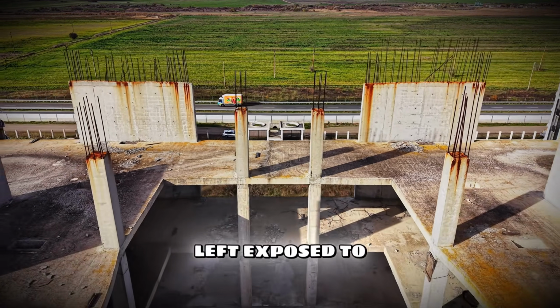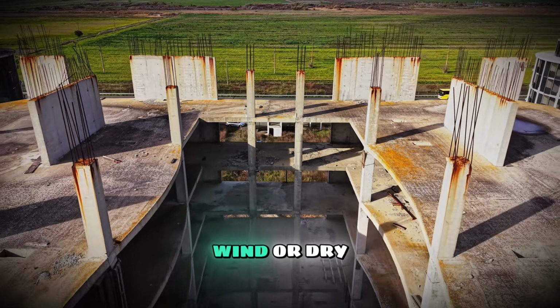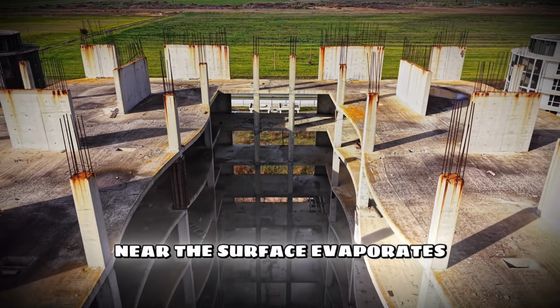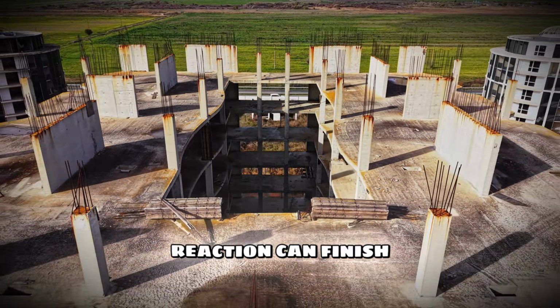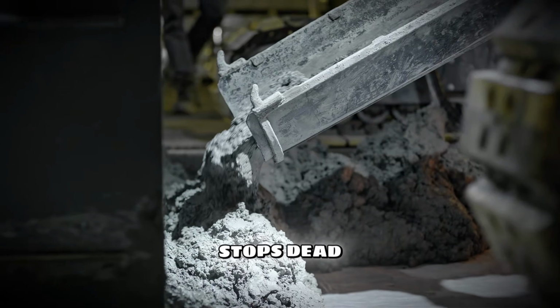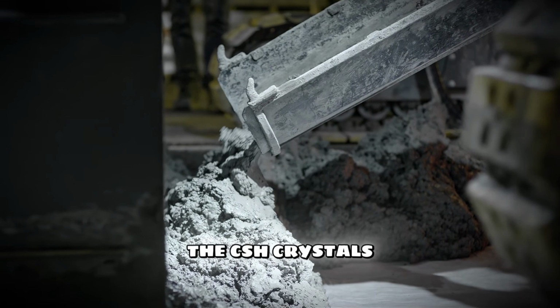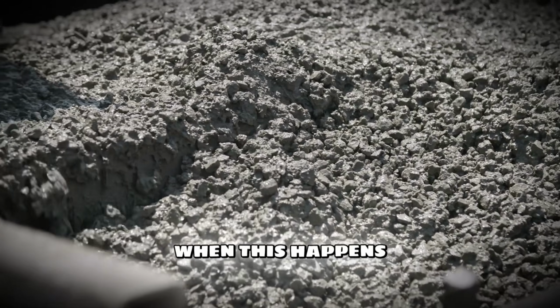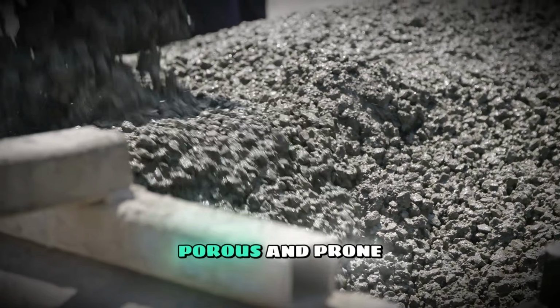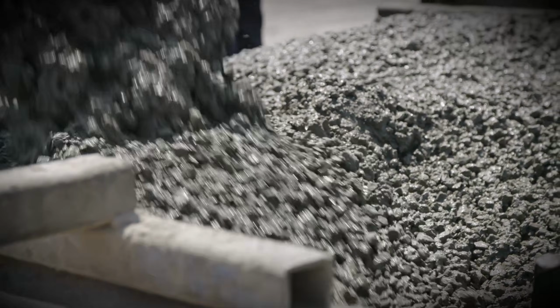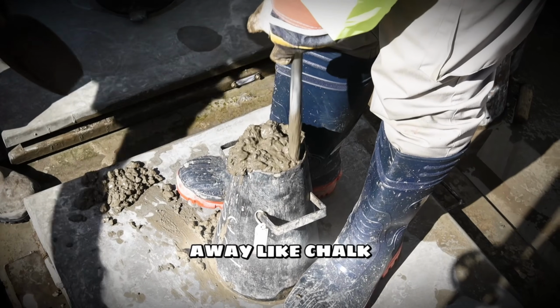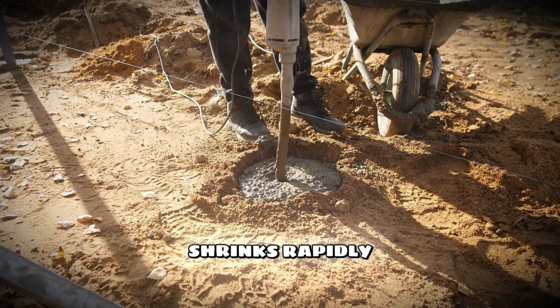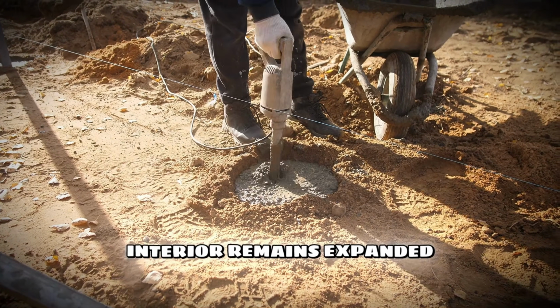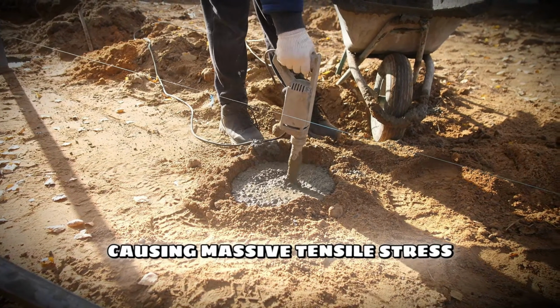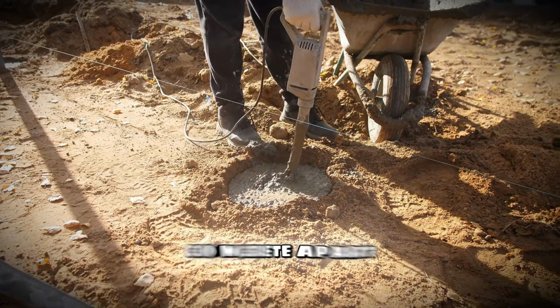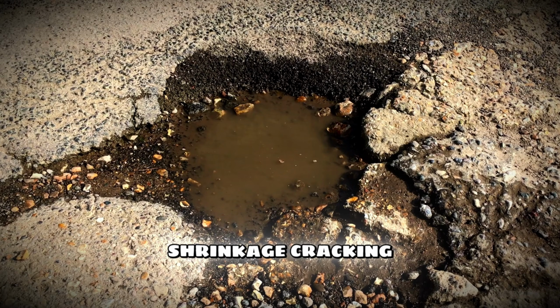If concrete is left exposed to the sun, wind, or dry air, the water near the surface evaporates before the chemical reaction can finish. The hydration process stops dead in its tracks. The CSH crystals never fully form. When this happens, you get a surface that is weak, porous, and prone to dusting, where the top layer literally rubs away like chalk. Worse, the surface shrinks rapidly while the damp interior remains expanded, causing massive tensile stress that rips the concrete apart, resulting in plastic shrinkage cracking.